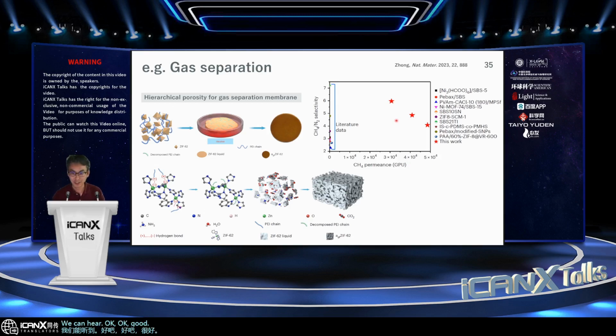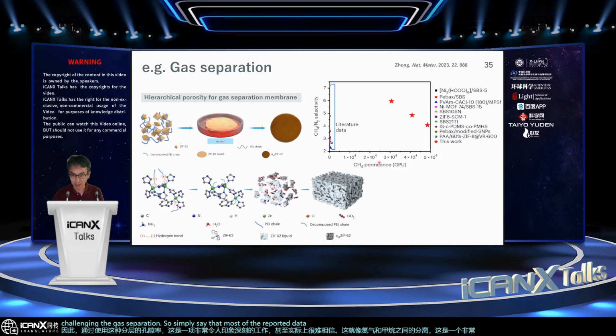Okay, good. And so by use of this hierarchical porosity, this is a very impressive work, even hard to believe actually. This is a gas separation between nitrogen and methane, which is very challenging. Simply said, most of the reported data is shown here, which means the gas permeability is pretty low. But this MOF glass membrane has a world record permeability as well as high selectivity.